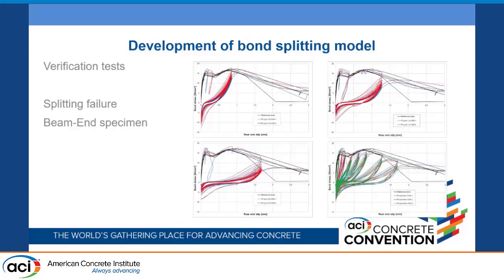And when we go to the splitting failure, where we use the beam end specimen and we reach the splitting failure, again we did the same thing at SU, 1.5 SU, 2 SU, and this was with the increasing slip protocol. So what we see is with the increasing slip protocol, we can capture the behavior of the reinforcing bar over the full range of interest, including also the hysteretic behavior, the residual behavior, and all the things.